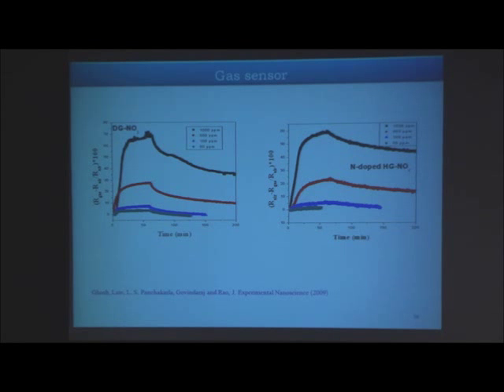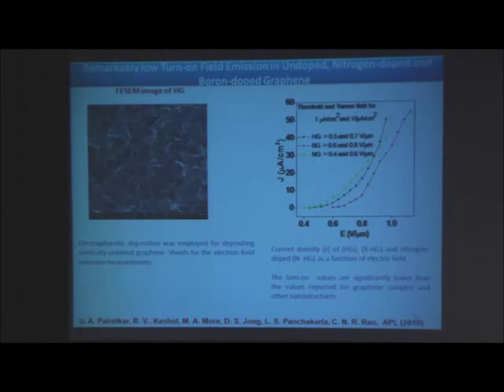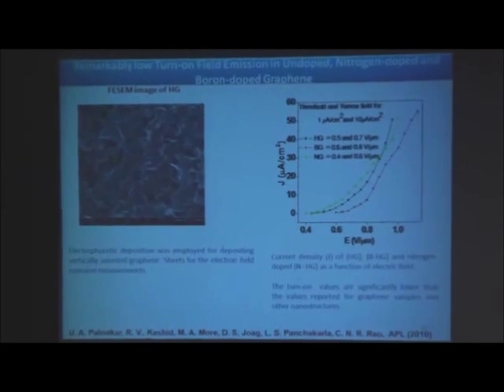Now, graphene has been used for many things, also for gas sensors. And recently there's some interest in Waterloo, so I added this because of you here. We have shown that boron and nitrogen-doped graphene have probably the lowest turn-on field emission, very low voltage. As you can see, 0.6 volt, you get wonderful electron emission out of these doped graphene. We have been looking into that. Okay, and you can see the field emission from graphene.